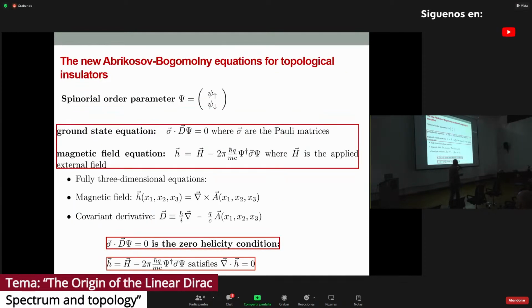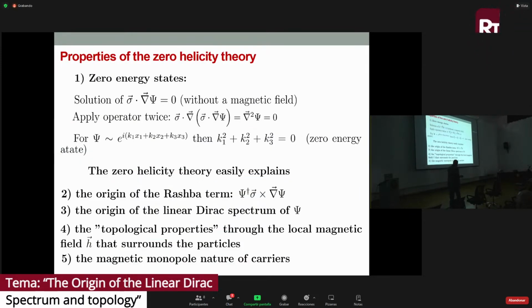Okay, what I am saying here is basically the following: if you include the spin in this field, this parameter, so to speak, and then you take the equation that describes the psi as being this one, which in fact is the zero helicity condition, okay, and you obtain the magnetic field like this, okay, these are the equations that describe topological insulators. Notice that this equation satisfies the divergence of the local field equal to 0 automatically. They are consistent. So my claim is that through these equations, you obtain several aspects of